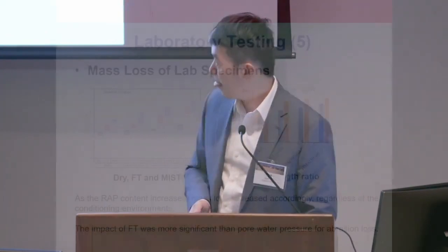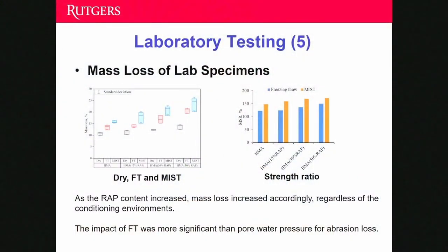And then we measured the mass loss of the lab specimens after conducting the Cantabro test. And the results are very straightforward. As the wrap content increased, mass loss increased regardless of the conditioning environment. But different from IDT and the interface condition, we found the freezing thaw is more significant than moisture conditioning for the abrasion loss.